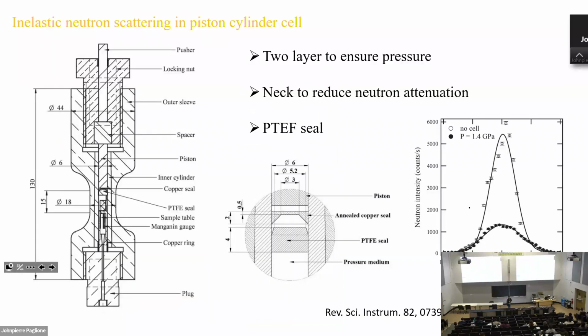As I mentioned, one advantage of this type of cell is the large sample volume. So this is their design for neutron scattering. The idea is that when the neutron goes through either beryllium copper or other material, the neutron will attenuate. So first they used two layers of cell to maintain the high pressure, but where the sample is, they make this neck type of thing to reduce the attenuation of the neutron. And again, they can achieve, this is only like 1/4 of the attenuation.